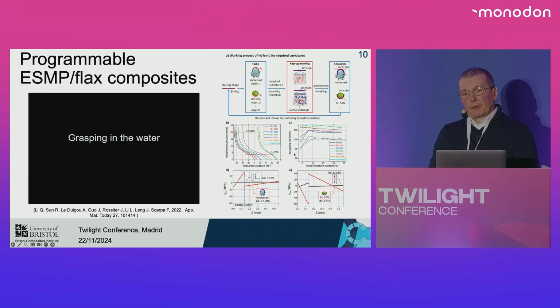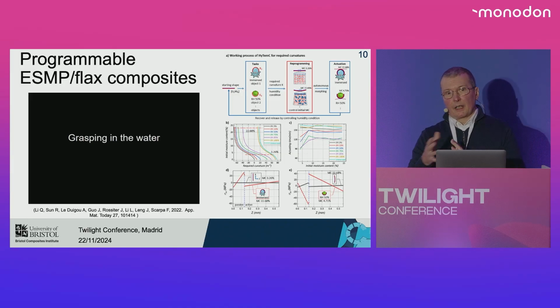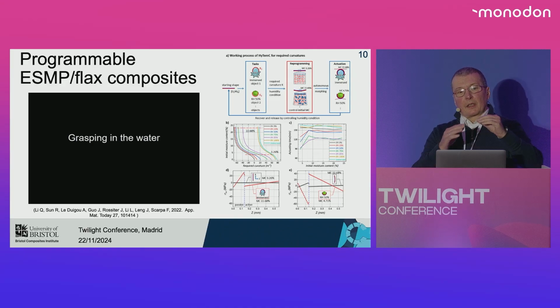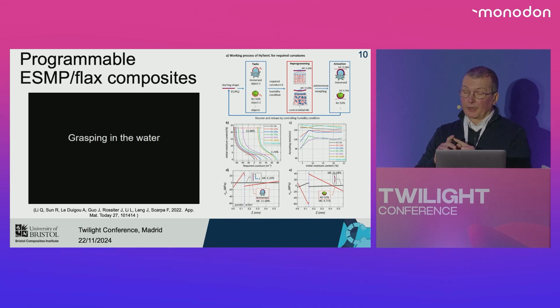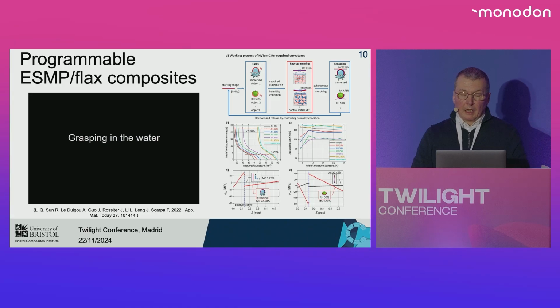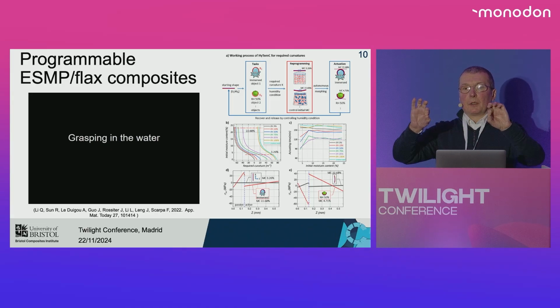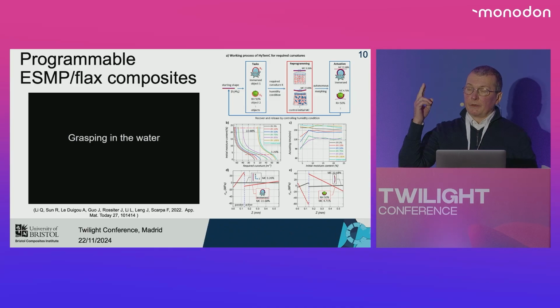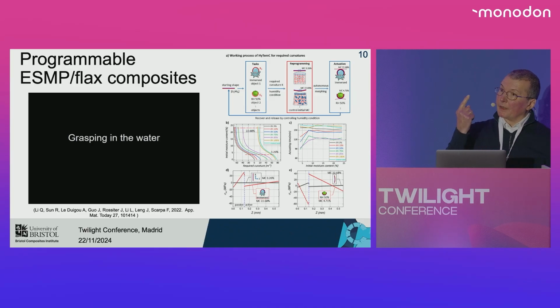We have made these types of composite using classical stacking sequence laminates and manufacturing processes, also using epoxy shape memory polymer matrices. The shape memory polymer matrices allow us to have one degree of freedom more in terms of design space. So we can combine initial moisture content inside the composites, the desired curvature also given by the stacking sequence, and the variation of the temperature through the Tg of the polymer. In other words, we did the same type of hygromorph actuator. We can store two different shapes, not the single one that we have seen before.